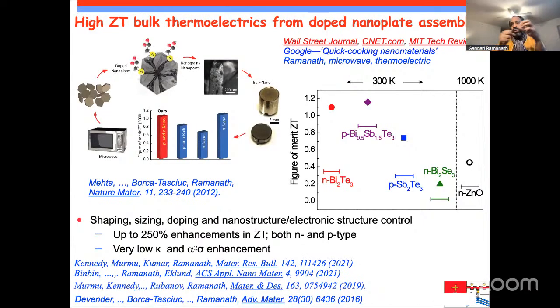And then what we did was we took these nanoplatelets and made them into bulk material where the nanostructuring is still retained. And lo and behold, what we found was quite a big breakthrough. We found that the figure of merit actually goes from around 0.3 to 1.1. I mean, this kind of large change, that too by a scalable process, made a big splash.